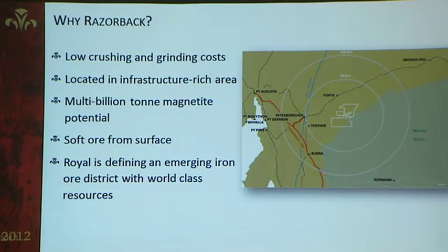And as a result, metallurgical testing has confirmed that the ore is soft, having relatively low crushing and grinding costs. And we found that the ore breaks along grain boundaries, not across the crystal faces. Therefore, we need less than half the power than it would be to actually crush an ordinary BIF.